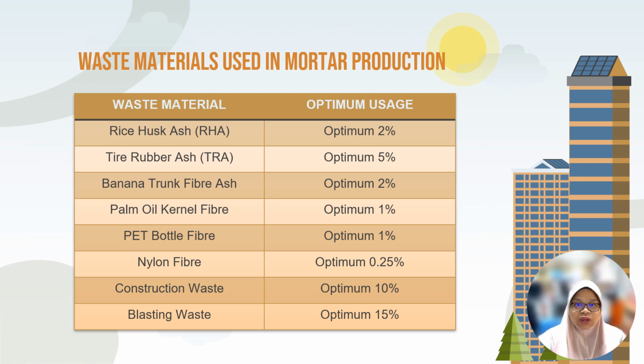The figures show the optimal percentage replacement of waste materials in mortar production. Researchers used replacement percentages from 0.5%, 1%, and 1.5% up to 5% for ash and fibers, while 5 to 50% for crushed materials. Literature research shows that the optimal percentage for each material is as follows. The mixture should not exceed this optimal value to maintain the functionality of the mortar in construction.